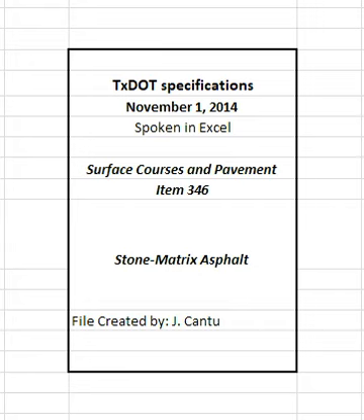Take immediate corrective action if the engineer's laboratory-molded density on any sublot is less than 95% or greater than 97% to bring the mixture within these tolerances. The engineer may suspend operations if the contractor's corrective actions do not produce acceptable results. The engineer will allow production to resume when the proposed corrective action is likely to yield acceptable results.